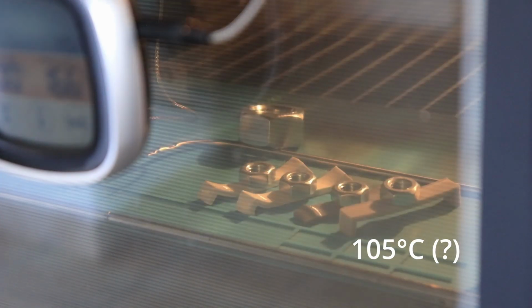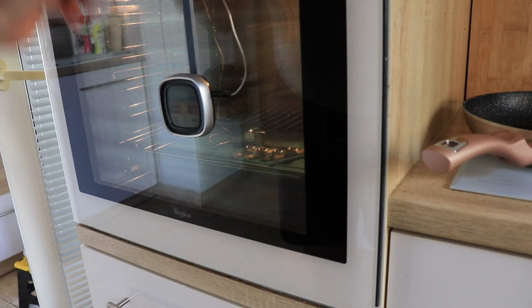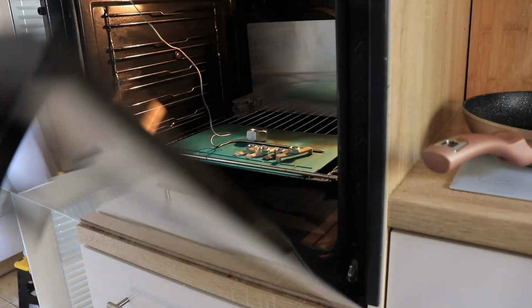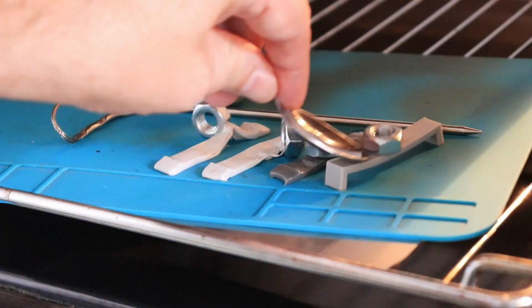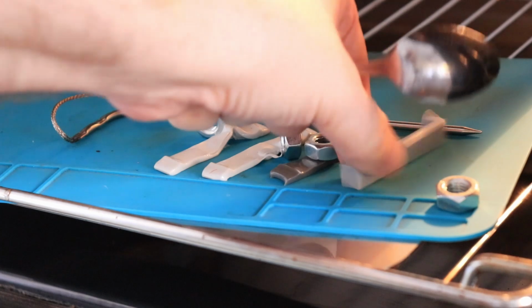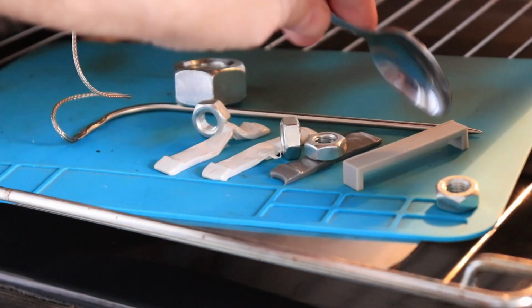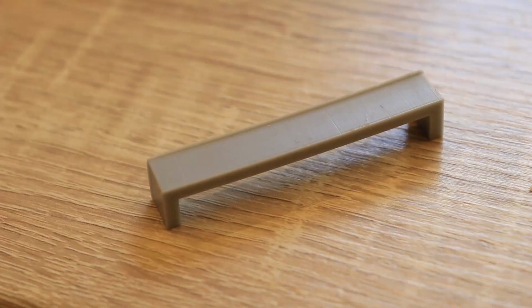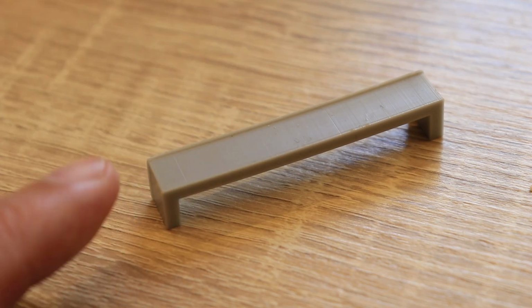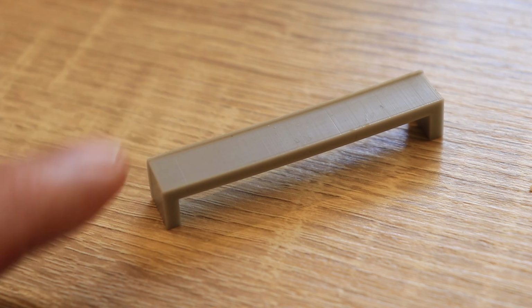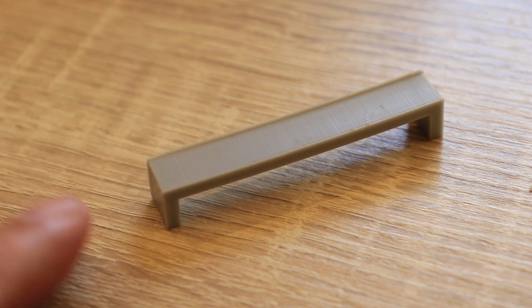I went up to 180 degrees Celsius. For the moment the light turned off, but no additional deformations on it. So the real big question is when it starts with the softening, so at which temperature can it be used? Well, because of the other materials in this test, I stopped the experiment at 180 degrees Celsius, but even at this temperature it was already very soft, so we cannot use it at this temperature.